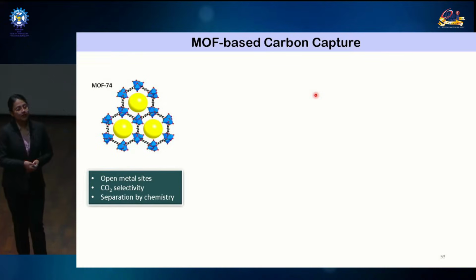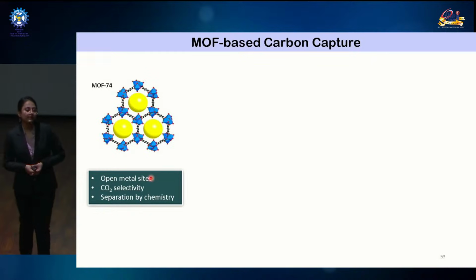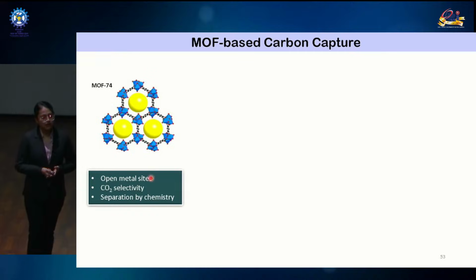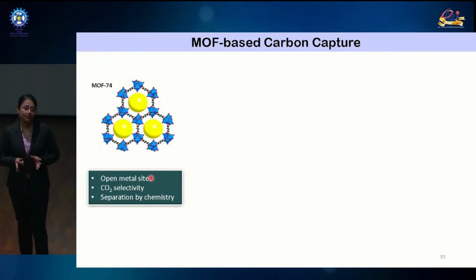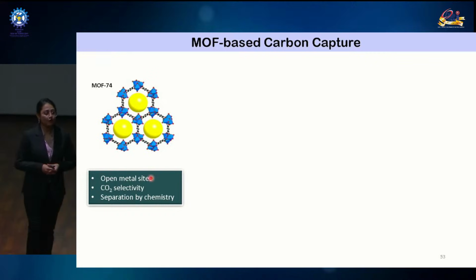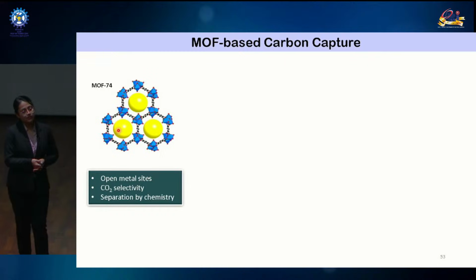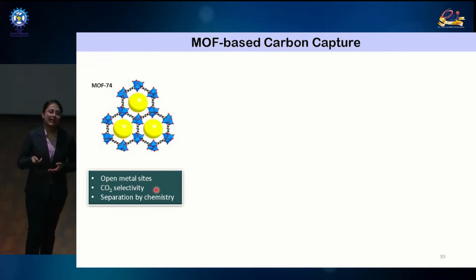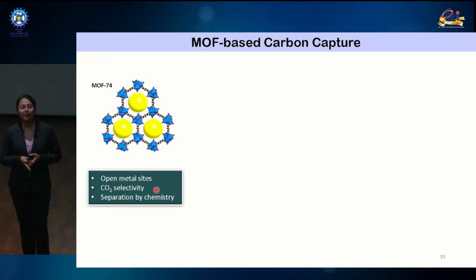So, based on the molecular designing toolkit devised by Omar Yaghi, he went on to design MOF-74. This was a major landmark contribution by Omar Yaghi, since it had high selectivity for carbon dioxide. This particular structure has a striking feature of open metal sites, that is, the metal centers are exposed, lining the pores. It showed exceptional selectivity and strongly bound carbon dioxide even in the presence of gas mixtures.